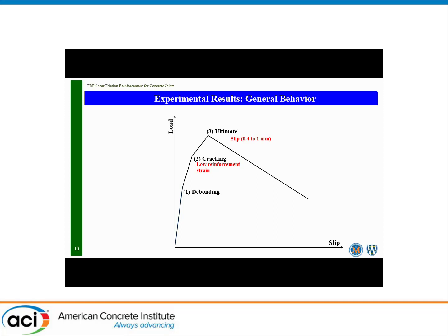Once a shear crack develops at the interface between the two parts, and if enough shear friction reinforcement was provided, the interface will continue carrying more load, but at a much lower post-cracking stiffness, until the point where the steel reinforcement totally yields. A sudden brittle failure will then take place at the interface.